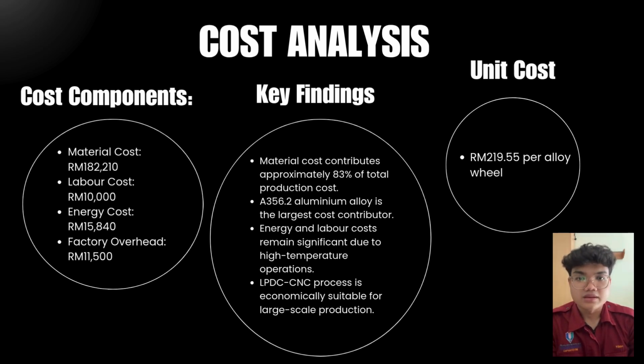From the result, material cost contributes approximately 83% of the total manufacturing cost, making it the largest expense in production. This is mainly because a large amount of A356.2 aluminium alloy is required to manufacture the wheels. When divided by the production quantity, the manufacturing cost per wheel is 219.55. This result indicates that the LPDC CNC manufacturing process is economically feasible for medium to high volume production.